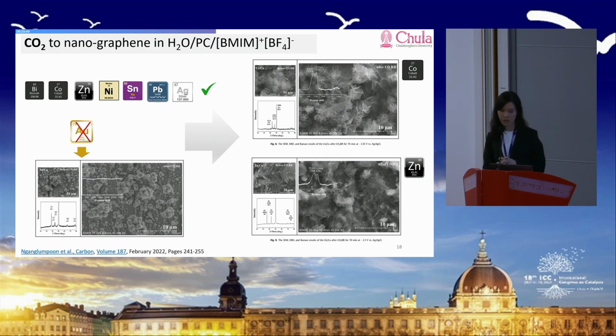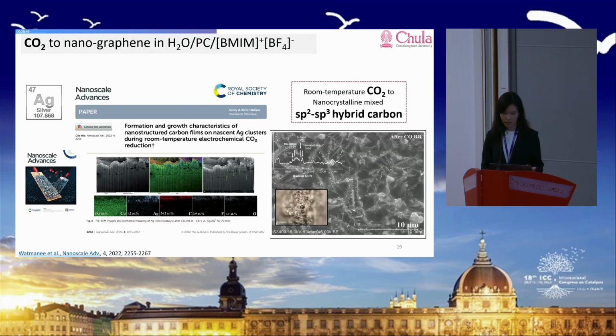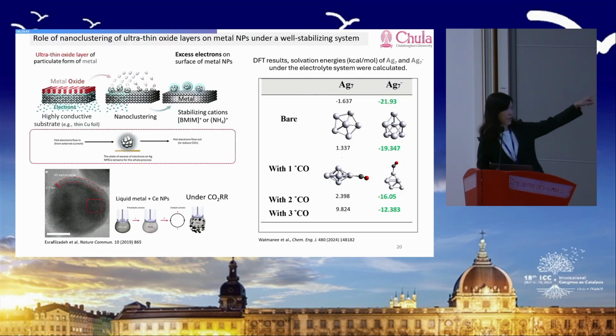on these metal particles. And we looked up the literature and found some work from before ours, from a group in Australia. I think they used cerium nanoparticles, and then under CO2 reduction reaction, they also ended up with a lot of carbon as a product. That's a cerium nanoparticle in a liquid metal system. And they proposed that the reduction of the thin oxide layers may have something to do with this pathway, but there's no further explanation from there.